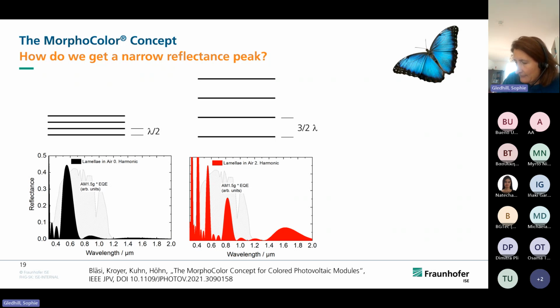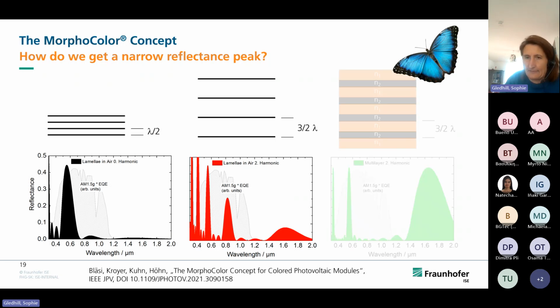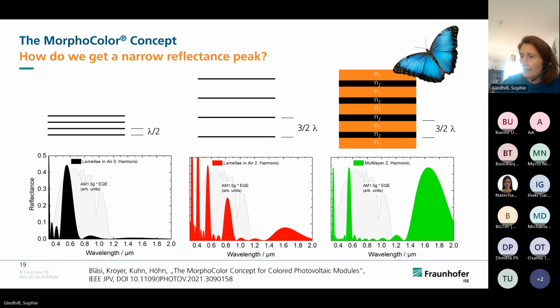But that's at a cost. The narrow peak width is desirable for the PV. But now we've got 2 unwanted additional peaks reflecting in the solar spectrum. At this point, it's important to note that the simple Bragg model does not describe the system correctly, since it assumes infinitely thin lamella. If you have layers of a defined thickness, then you start having vanishing peaks due to destructive interference. And here in our second order harmonic system, our first and third peaks are vanishing, and we're left with our main peak with a narrow width in the range of our solar spectrum.